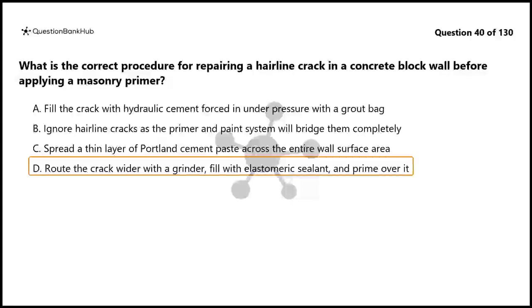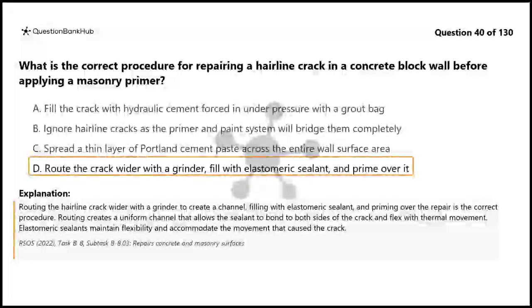The correct answer is D. Routing the hairline crack wider with a grinder to create a channel, filling with elastomeric sealant, and priming over the repair is the correct procedure. Routing creates a uniform channel that allows the sealant to bond to both sides of the crack and flex with thermal movement. Elastomeric sealants maintain flexibility and accommodate the movement that caused the crack.